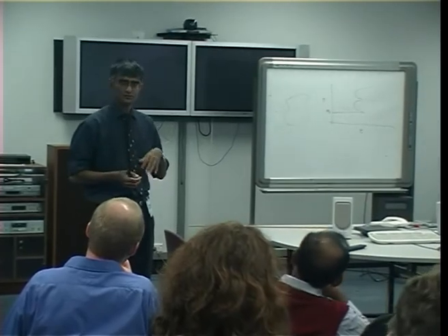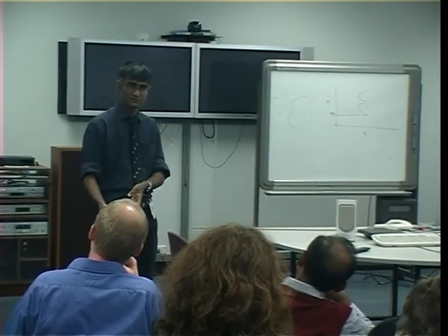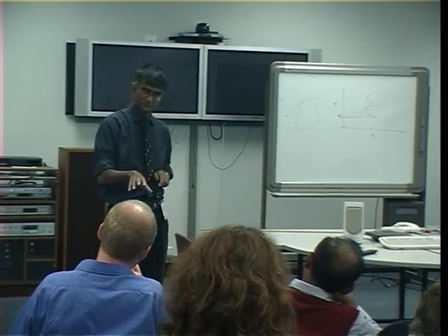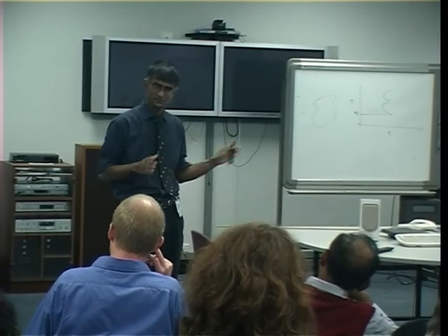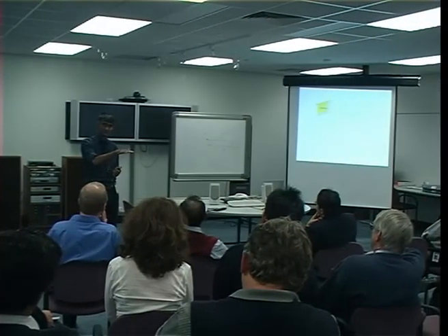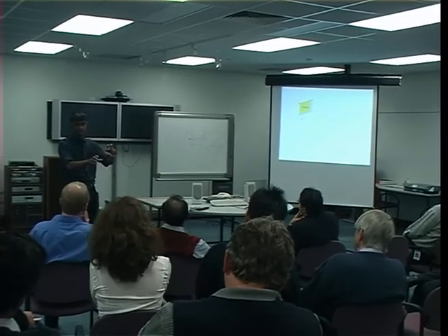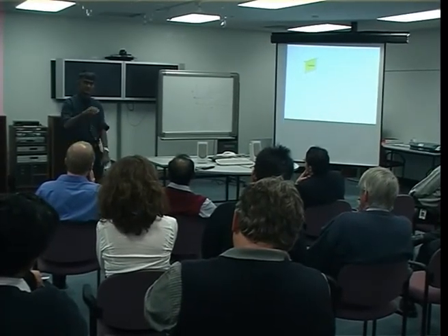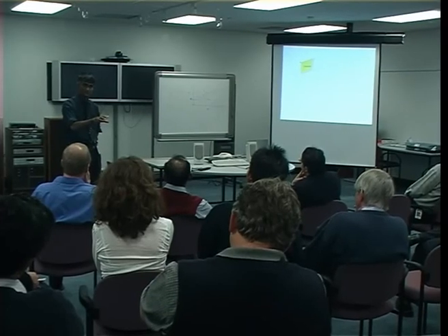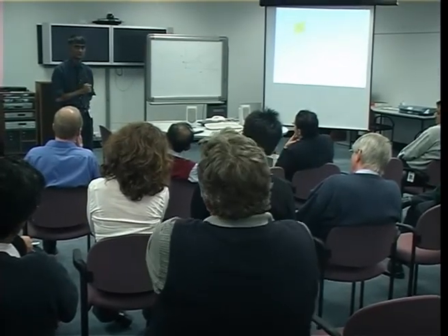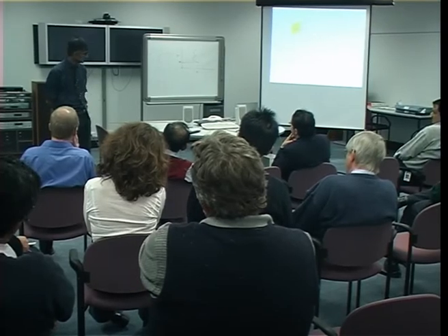You can use the same theory to start with body centered cubic and go to face centered cubic, and in copper alloys, you actually go from body centered cubic to face centered cubic. But in principle, there's absolutely no difference in the theory, and it even applies to really complicated things like plutonium, which actually melts at 600 degrees centigrade, and the solids that form are less dense than the liquid. So they're very unstable, and they undergo a whole series of Martensite transformations. But the crystal structures are incredibly complicated. But the same theory applies. Similarly, uranium alloys, some of the ceramics are complicated. But in principle, they all are explained by this theory.